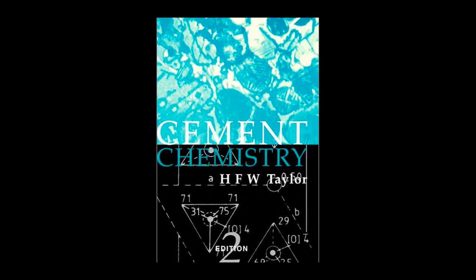So that's like a progress marker. It's the key chemical indicator. This free lime is highly reactive, and it must subsequently react with the newly released silica and alumina to form the necessary silicates, C3S and C2S. The peak of that free lime is the signal that the components are fully broken down and ready for the synthesis reaction. So before the final clinkering phase occurs near 1450 degrees, you can detect several intermediate products: free lime,